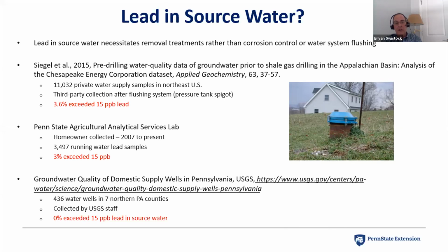I know in dealing with those 3% that have submitted samples to our lab that had running water samples, I know in follow-up with a lot of those folks, we found that they simply did not flush the sample long enough. And when we followed up and went through another set of samples where we flushed an extra period of time or looked at the pressure tank specifically and flushing of the pressure tank, we found that a lot of those samples turned out to not have lead in the source water. So I think it's safe to say it's a very rare event. I can really only think of a few cases that I've dealt with where we could absolutely say that lead did occur in the source water due to industrial contamination or due to some naturally occurring source of lead.